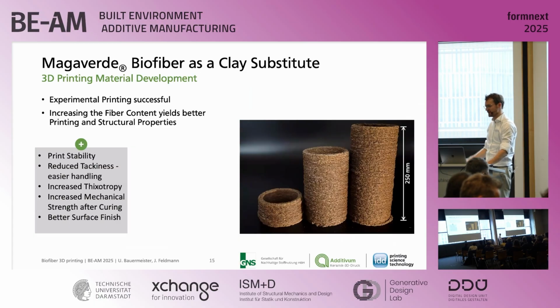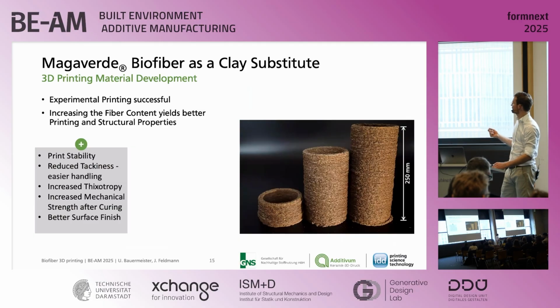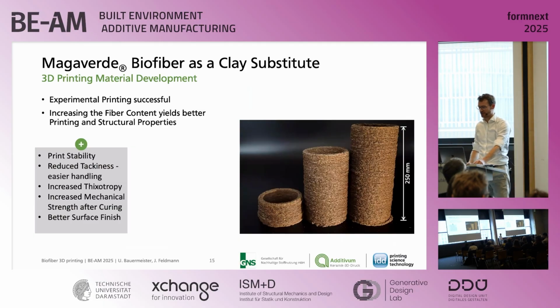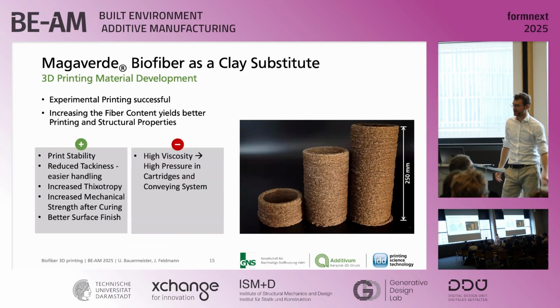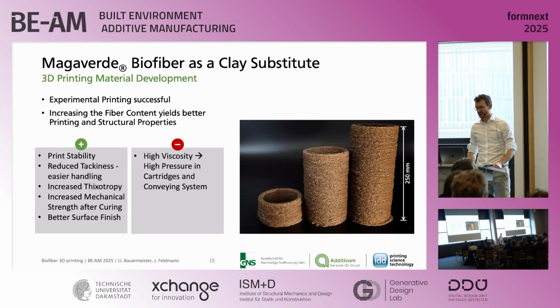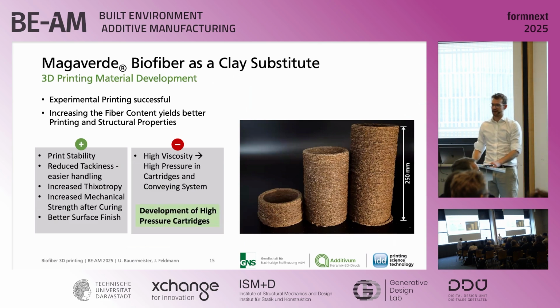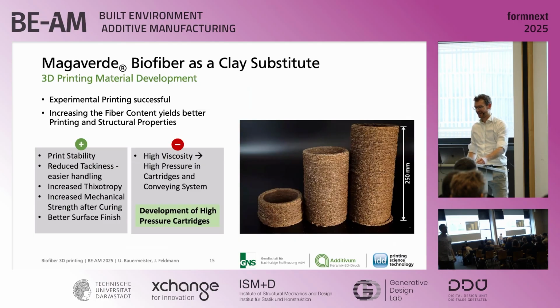As I mentioned, reduced tackiness, increased thixotropy, so inside the nozzle everything is still fairly liquid, and once it's stationary and placed, it stays put. But we also increased the mechanical properties of the material, so it got harder and firmer after printing and a better surface finish. The only downside really is that we have high viscosities, of course, and therefore also more stress in the whole material conveying system, so we had to tackle this by improving our cartridges and everything basically. So everything that can break broke, and we fixed it and made it stronger, and it helped a lot.